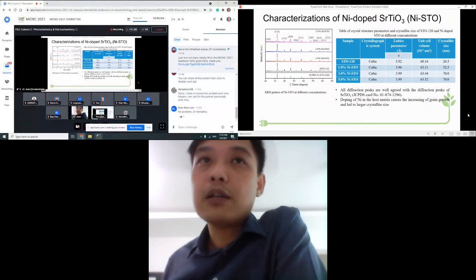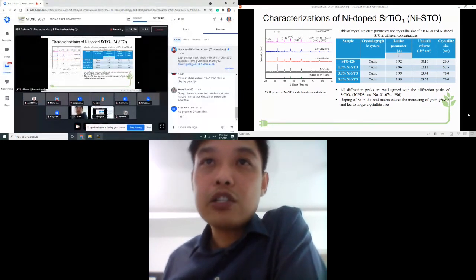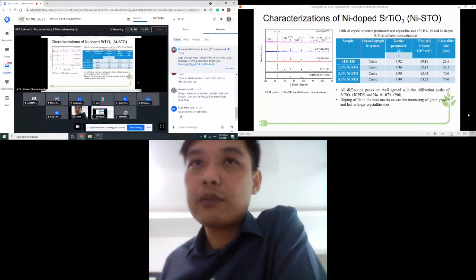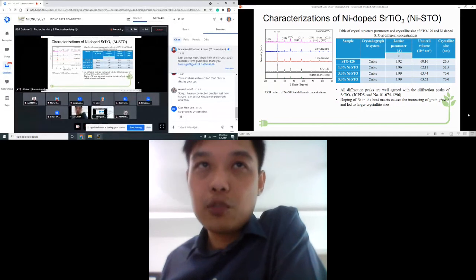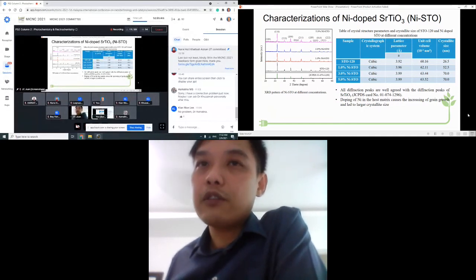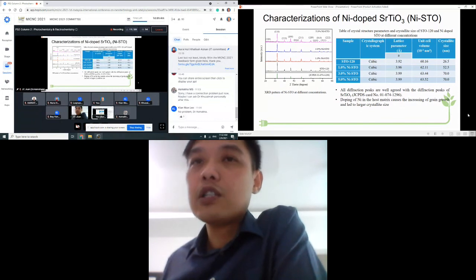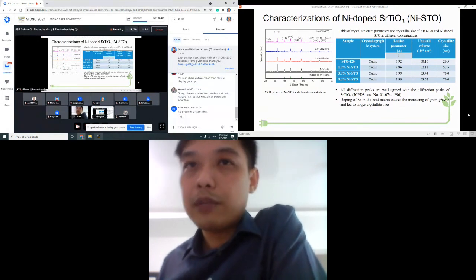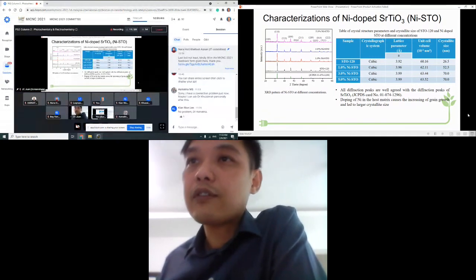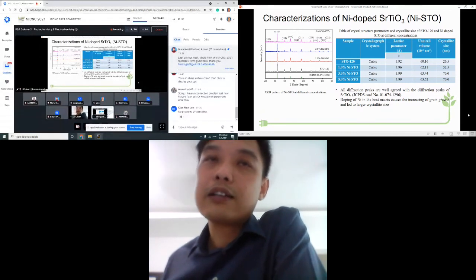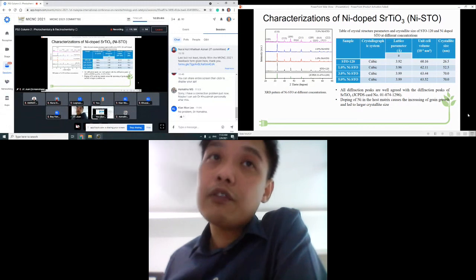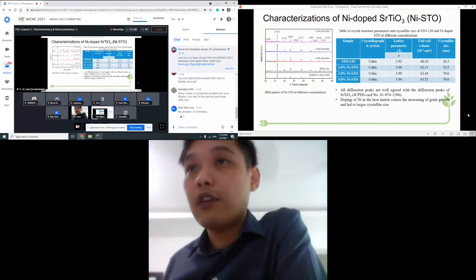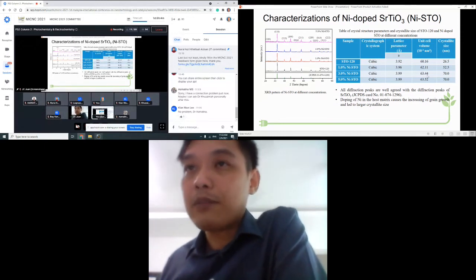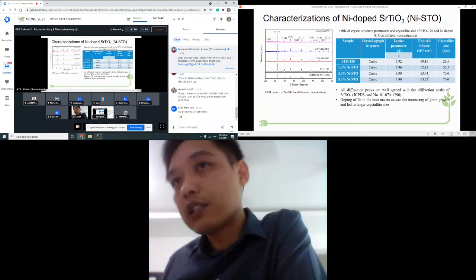And you can see from this XRD, we managed to synthesize the STO, the strontium titanate. And after doping, the structure did not change much. So this is good news, it still remains as a perovskite material. They did not destroy the strontium titanate material. But doping of nickel in the host material causes an increase in grain growth and leads to a larger crystal size. This is what we observe, because the broadening of the XRD peak shows that the crystal size becomes bigger. You can see from here the unit cells become slightly bigger, from 60 to 62, 63.